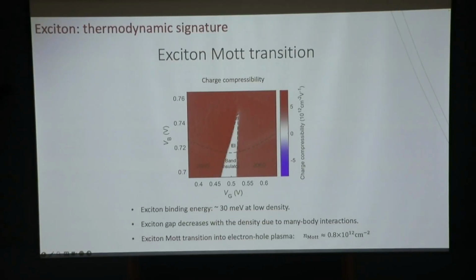By looking at this, we can also estimate the exciton binding energy. Let's say I increase right above this dashed curve line, we can see that there is about a 30 millivolt range where I cannot dope electrons and holes. That corresponds to an exciton binding energy of about 30 milli-electron volts. If you think about the room temperature thermal energy being 25 meV, this is a respectable exciton binding energy. Further, we can see the width becomes narrower when we increase the exciton density. That tells us the many-body exciton interaction will renormalize the exciton binding energy up to a critical density. Beyond that critical density, it becomes a free-moving electron-hole plasma. The exciton binding energy becomes zero, and that's known as the exciton Mott transition.